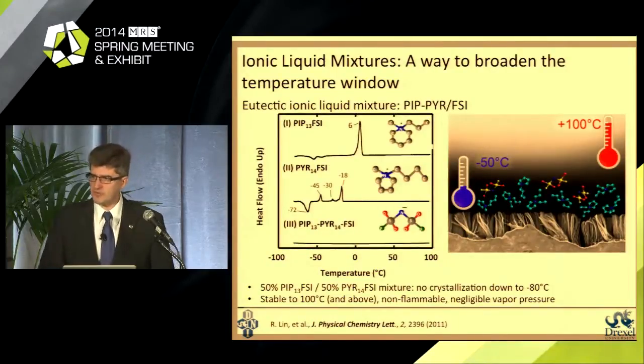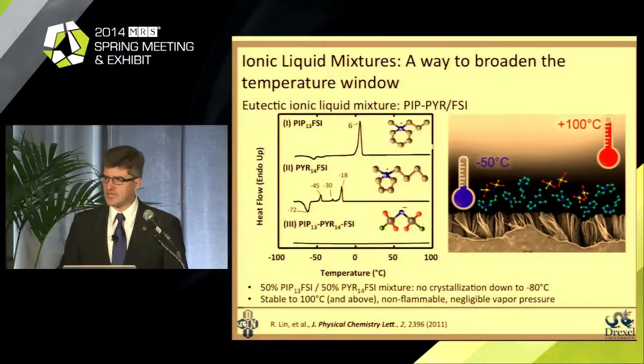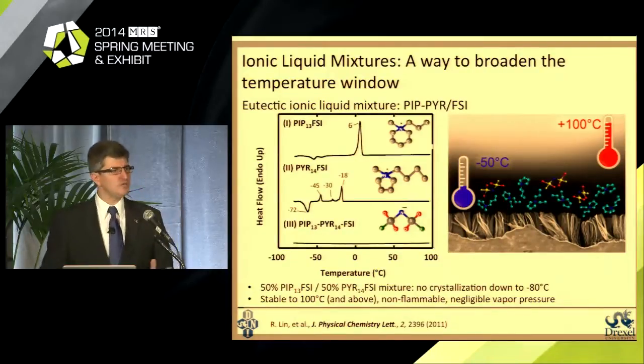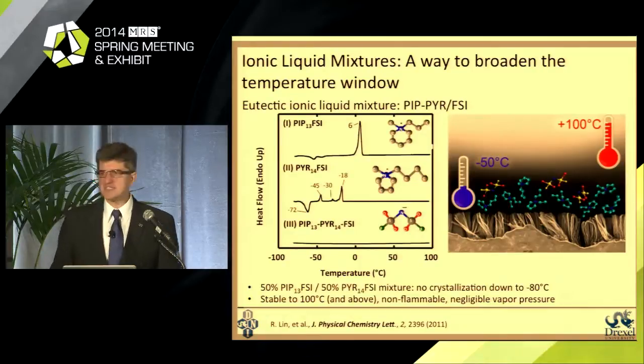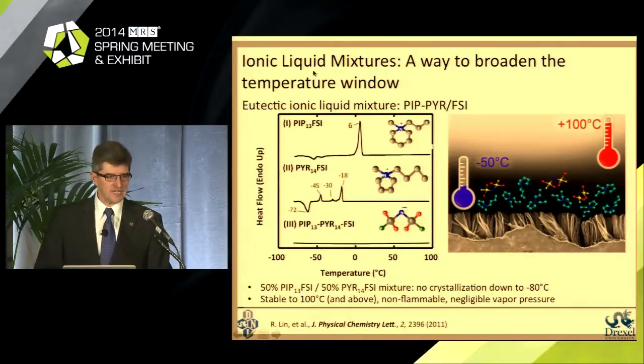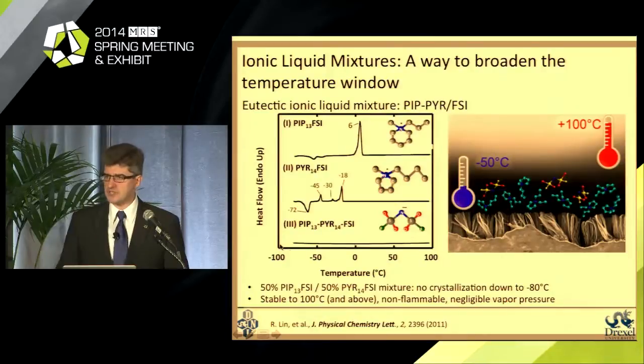I mentioned to you before that, for example, for ionic liquid electrolytes, people could only do experiments at elevated temperature and design devices with porous carbon that would work at temperatures above room temperature. However, when we learned and realized that by using open structures, we eliminate large diffusion limitations, what we did, we took a mix of ionic liquids, eutectic mix, that doesn't freeze down to -80 degrees C. It may have lower conductivity, high viscosity.